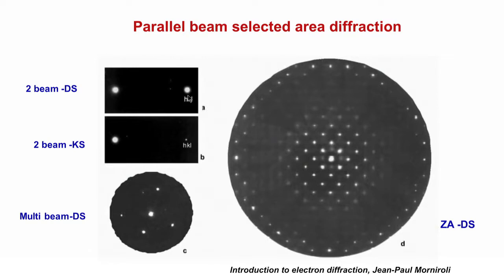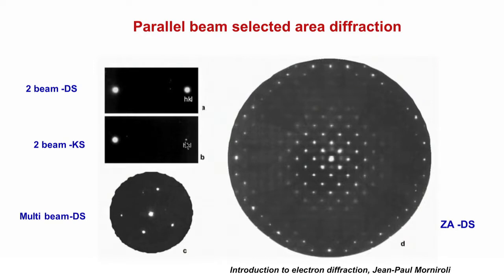In a conventional parallel beam selected area diffraction with two-beam condition, there is a central spot and a diffracted spot — both very strong due to dynamical scattering. Under kinematical conditions, the central spot is strong and the diffracted spot is weak. In precession electron diffraction, a small focused beam is made to fall on the sample and is rotated around the optic axis over a precession angle θ. The precessed beam is then de-precessed by applying voltages to coils in the microscope — either by voltage or magnetic field — to bring all beam positions back to a single point in the diffraction plane.